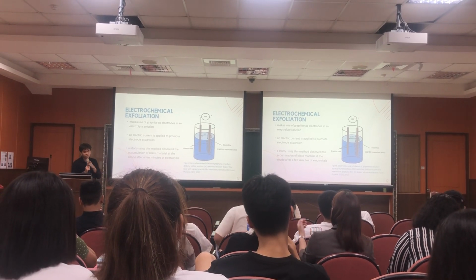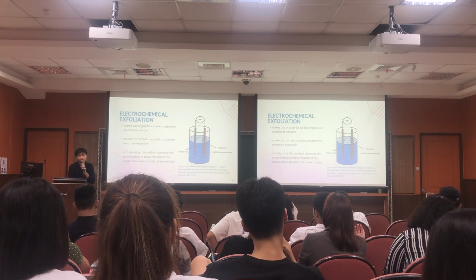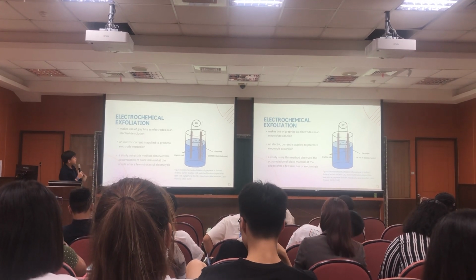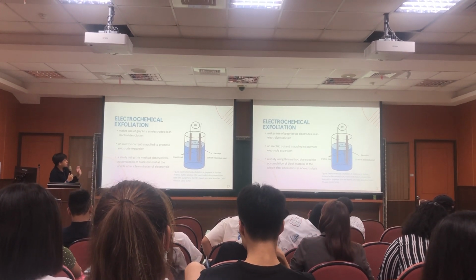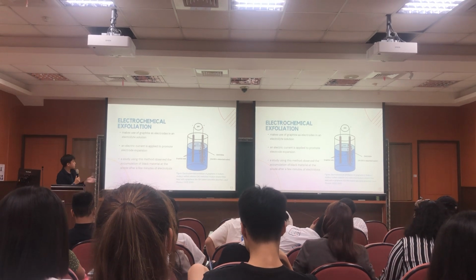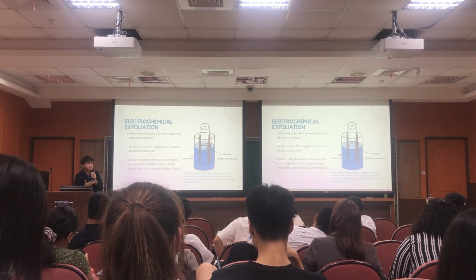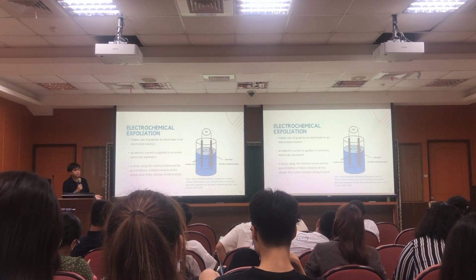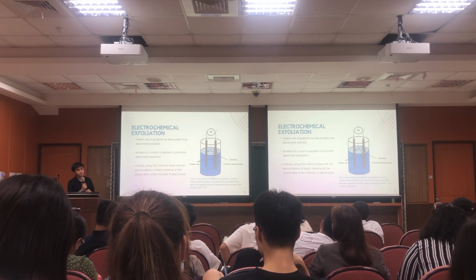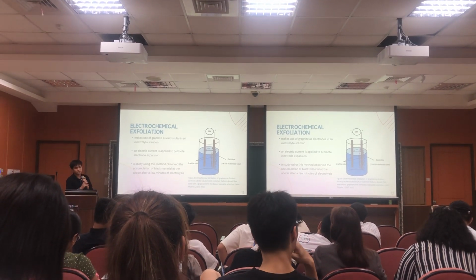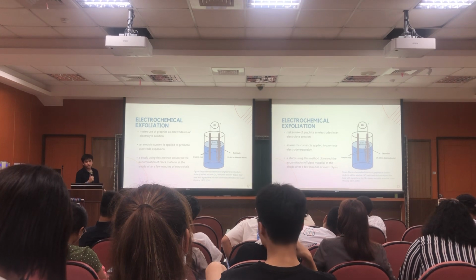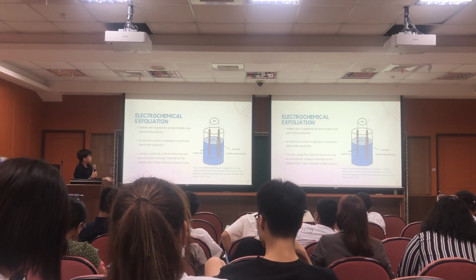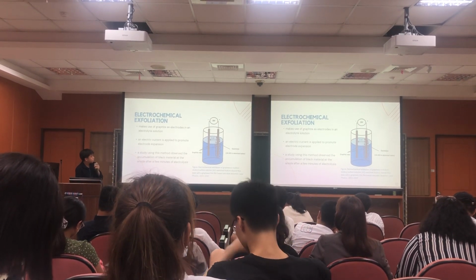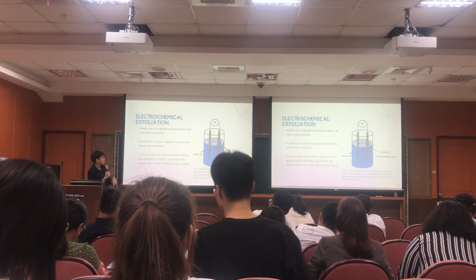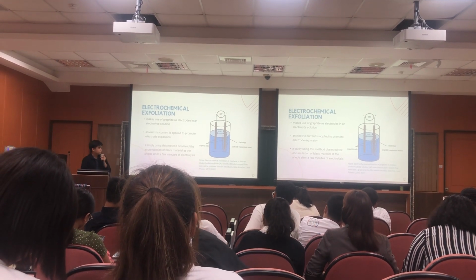Moving on, let's look at electrochemical exfoliation. Here, graphite is used as electrodes in an electrolyte solution. You apply a current, and after a few minutes, you should observe a black material at the anode once you start electrolysis. Post-processing steps after collecting the black material show us that these materials are graphene flakes. Our figure on the right shows us a demonstration of electrochemical exfoliation of graphene in a 1% sodium dodecyl sulfate solution.